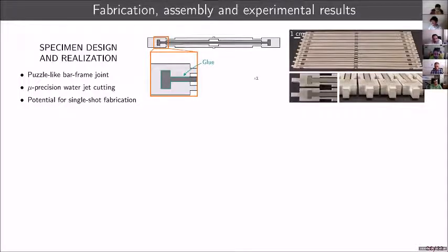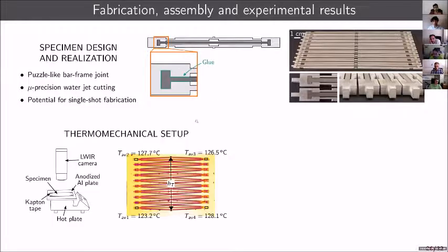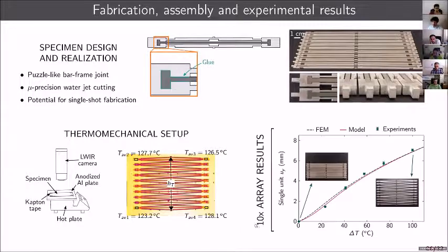We fabricated these structures out of titanium and aluminum. We slightly changed the design so that there are puzzle-like joints that allow better bonding between the two materials, and we used glue. So these are the thermomechanical setup. We have a hot plate, on top we have our structure, and we have a thermal camera that allows us both to look at the temperature and to measure the elongation of the structure. We do that by pixel counting.